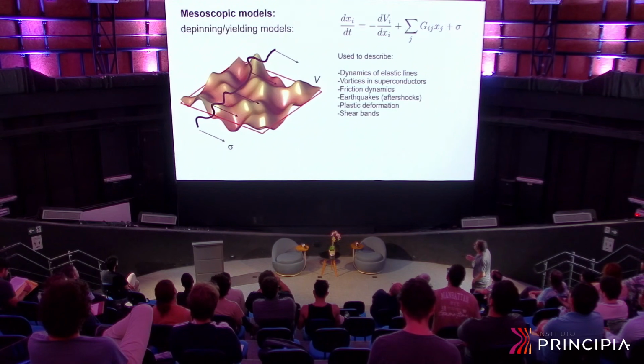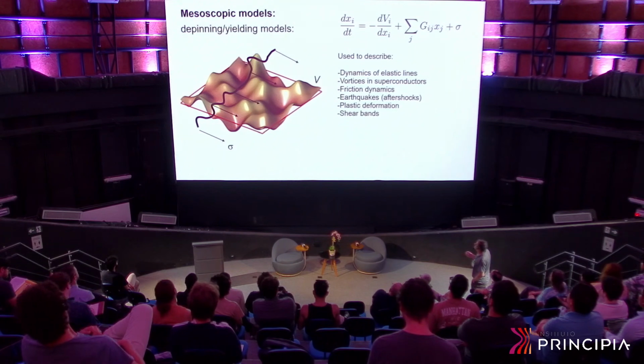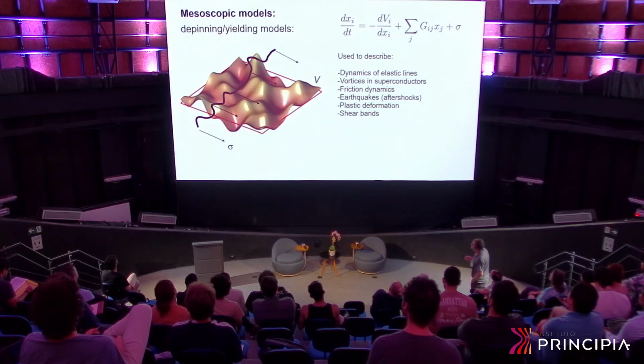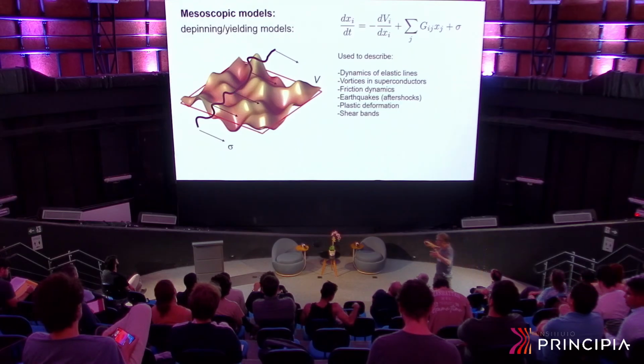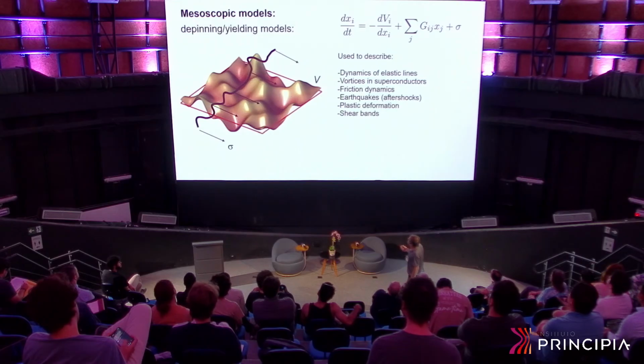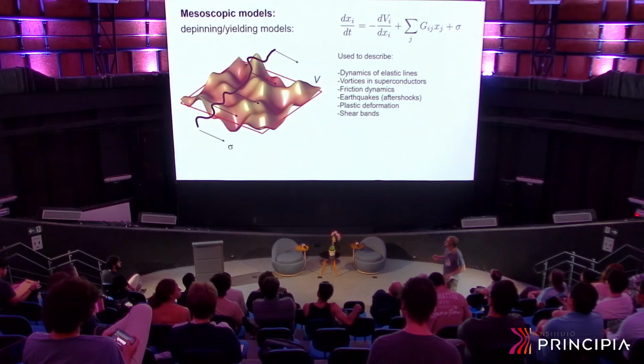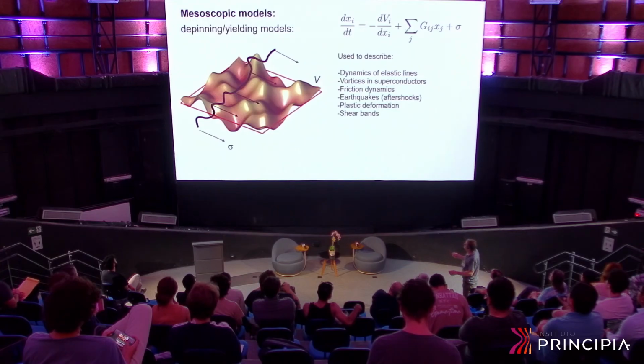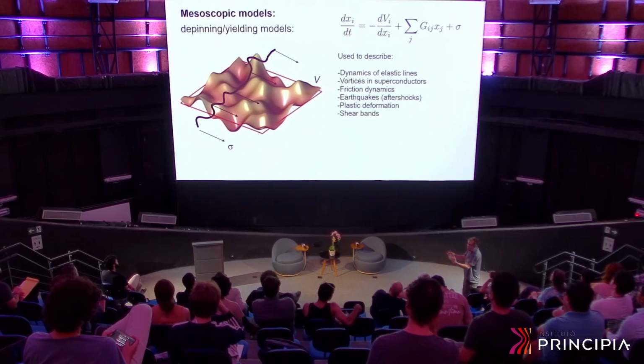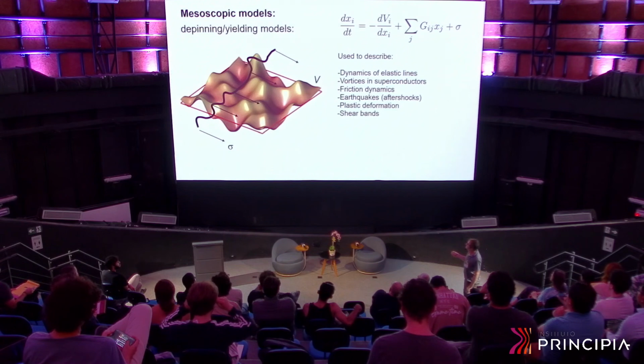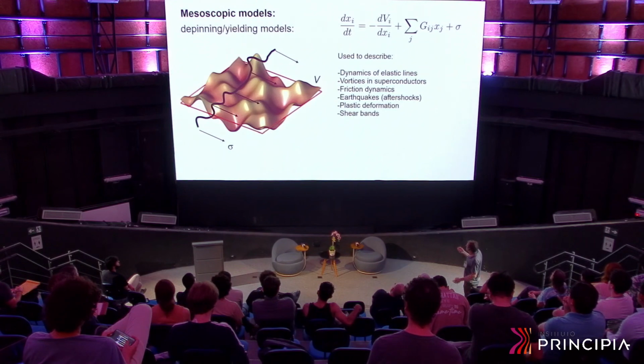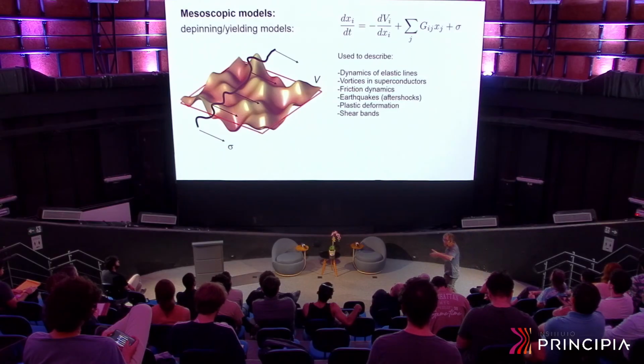But to give a flavor of the kind of modeling this is, let me consider the simplest case, which is the case of an elastic string, essentially an elastic variety moving onto some disordered potential that will have some physical interpretation depending on the problem. But the point is that you have to drag this line on top of this potential, and it seems pretty clear that because of these highs and lows of the potential, if you apply a very low force, you will not be able to displace the string. By the way, the equation of motion that I consider is an overdamped dynamic equation.